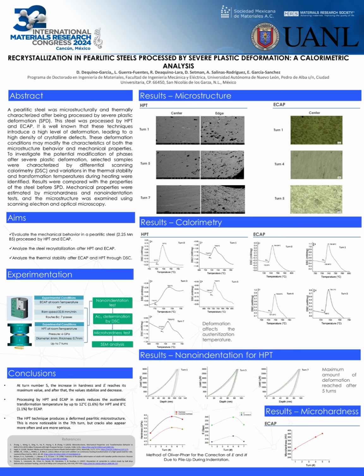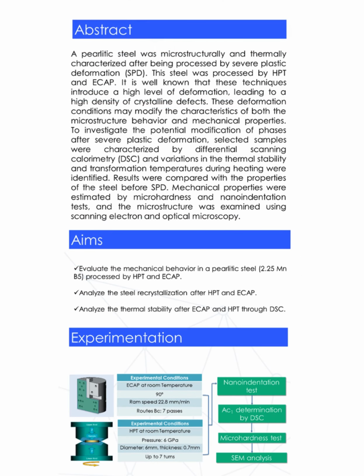Good day, everyone. I'm going to present the poster titled Recrystallization in Pearlitic Steels Processed by Severe Plastic Deformation, a Calorimetric Analysis. In this investigation, a pearlitic steel was analyzed microstructurally and thermally after undergoing severe plastic deformation, SPD, through techniques such as high-pressure torsion, HPT, and equal-channel angular pressing, ECAP. These methods introduce significant deformation, which increases the density of crystalline defects.